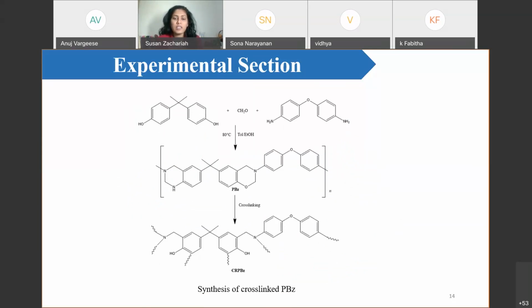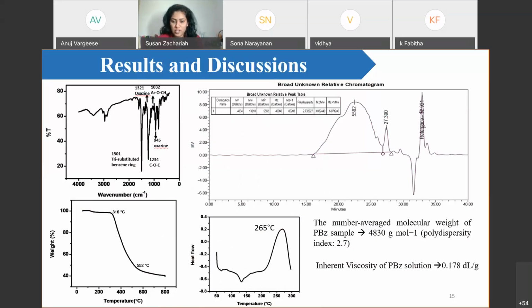This is the preparation of polybenzoxazine. A primary amine and formaldehyde are mixed in solvent, toluene and ethanol, and heated at 80 degrees Celsius. Finally, it is cross-linked, and we got the cross-linked PBz material. Some of the resultant discussions I have given. To check the properties of benzoxazine, we have checked the FTIR, TGA, DSC, and GPC to find the number average molecular weight. These all we have done to check whether the PBz has the actual properties of the earlier works.